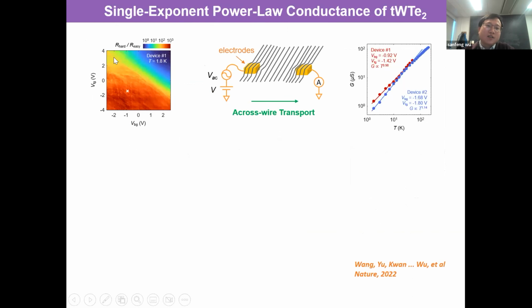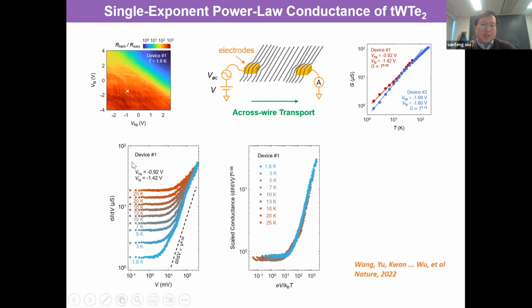So we parked the gate voltage on the hole side where you see strong anisotropy, and you measure the conductance along the wire. So immediately you see the data here, the conductance as a function of temperature on a log-log scale. So linear means power law, with exponent alpha around 1 in this case. You can also check differential conductance as a function of bias and temperature. In this plot, I'm showing you a variation of bias by more than 3 decades and temperature by more than 1 decade. And you can see that all this data is raw data. We just record the current and divide by the voltage.